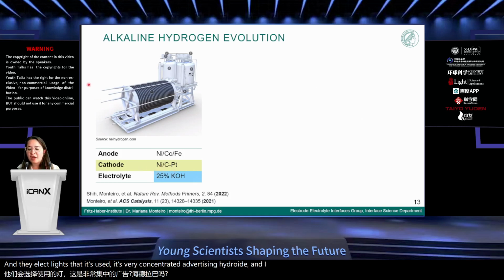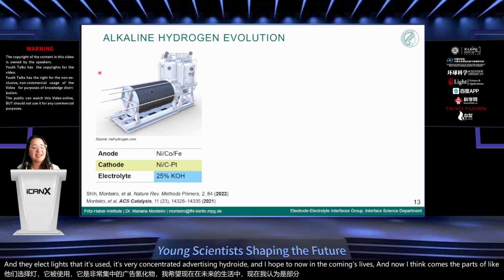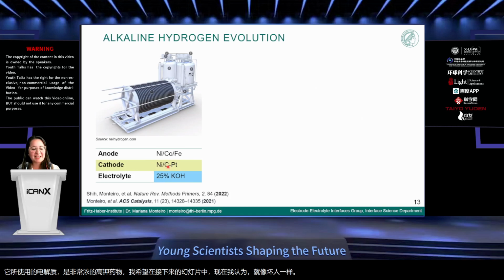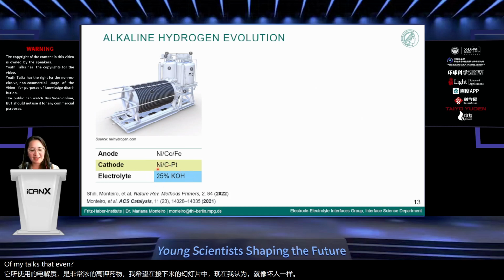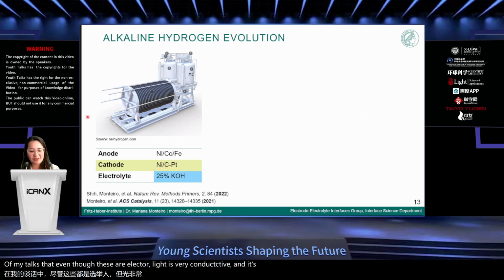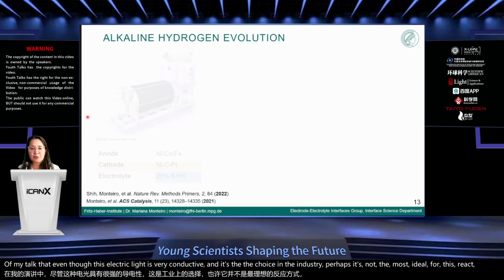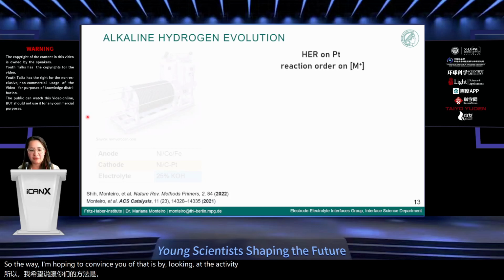And I hope to now, in the coming slides, and now I think comes the part of the villains of my talk: even though this electrolyte is very conductive and it's the choice in the industry, perhaps it's not the most ideal for this reaction. So the way I'm hoping to convince you of that is by looking at the activity of hydrogen evolution as a function of cation concentration. And with that, we make these reaction order plots.